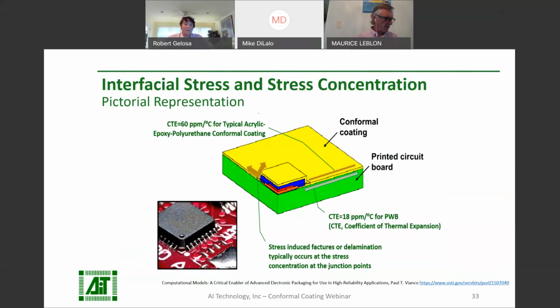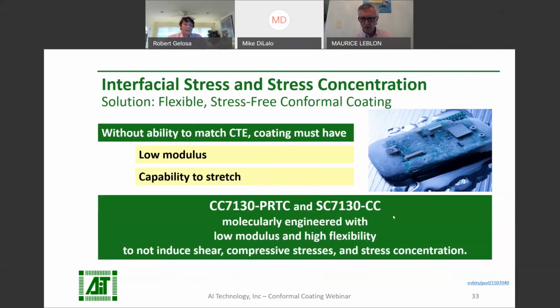Large circuit boards will have even more problems because the differential in expansion between the coating and the board will be even greater. And if the board has multiple high-profile components, it's going to cause corresponding points of stress concentration. Since no coatings out there can match the CTE of the boards, your coating needs to be able to stretch. Highly flexible or stress-free products have always been an expertise of AI technology. And we've continued this tradition with our conformal coatings.